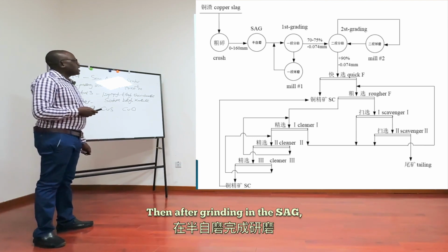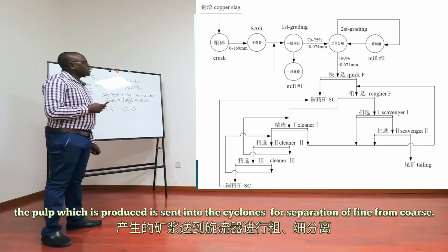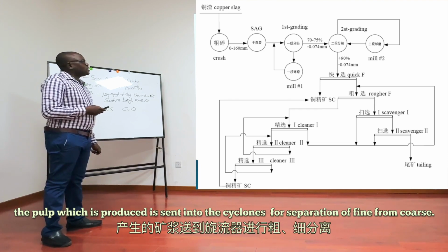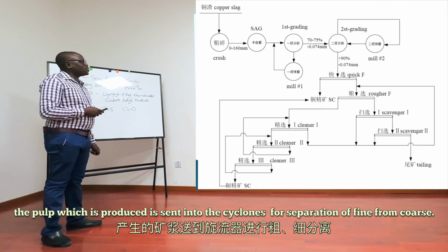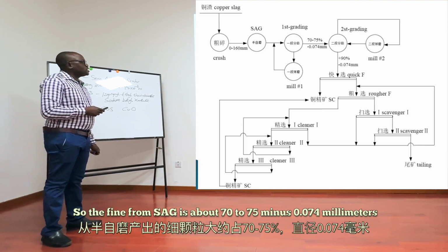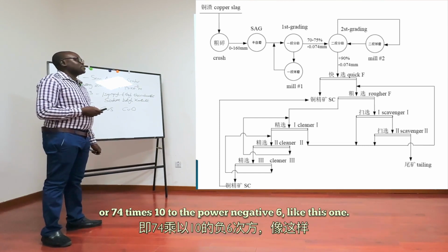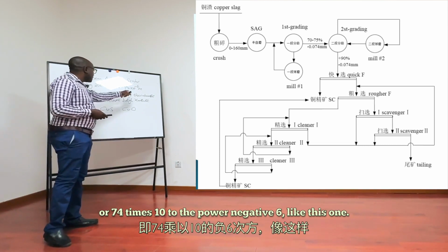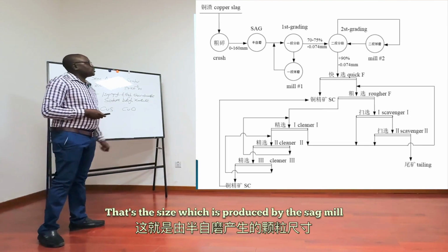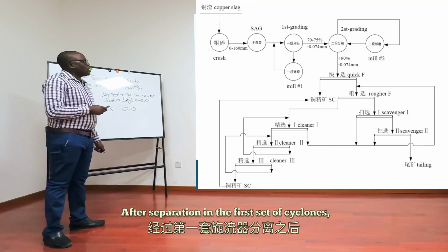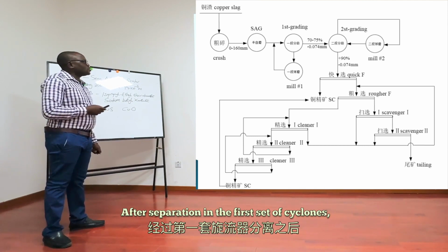Then after grinding in the SAG, the pulp which is produced is sent into the cyclones for separation of fine from coarse. So the fine from SAG is about 70 to 75% passing 0.074 millimeters, or 74 times 10 to the power negative 6 meters. That's the size which is produced by the SAG mill, or after separation in the first set of cyclones.